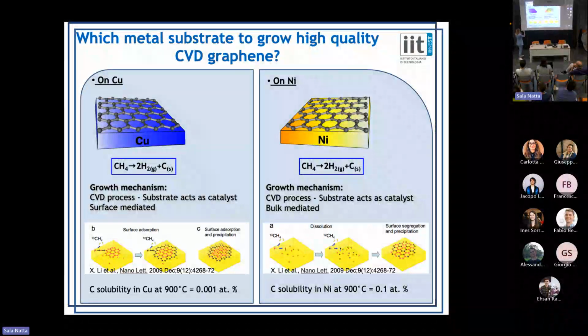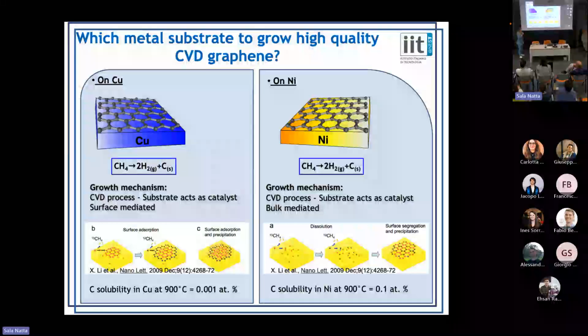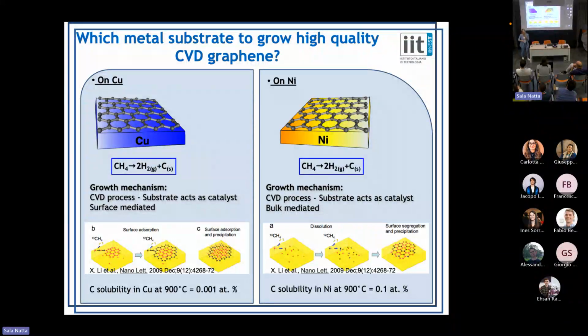Okay? But if we have a metal that really gets impregnated by carbon very easily, what happens is that when we cool down, all the carbon comes up, and then it's just amorphous carbon around, so it wouldn't work. We need a metal that has really low carbon solubility, that is just catalytically active to help us break the methane bonds and form graphene, but when we cool down, because our growth is finished and completed, we don't get carbon segregation on the surface. Okay, almost every metal, if it's not very high purity, has a lot of impurities.